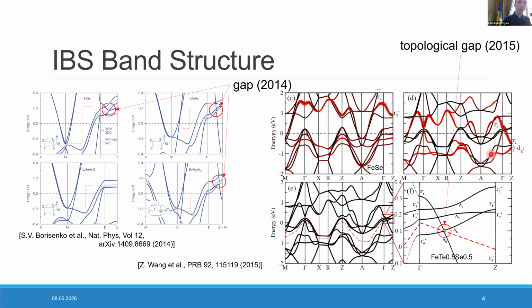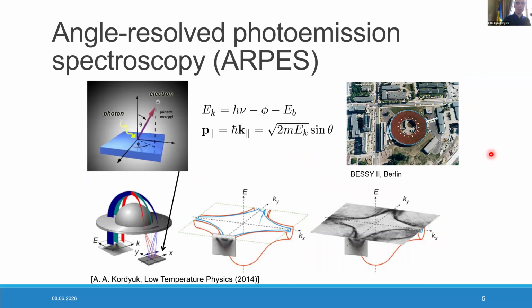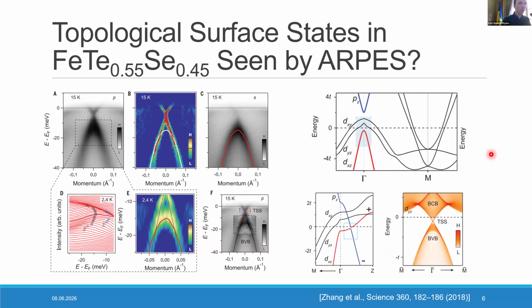And one of the ways to check that, and how people do that, is to do scanning tunneling microscopy to search for zero bias peaks, which are signatures of Majorana zero modes, but they can be strongly intertwined with other peaks coming from CDGM, and it's tricky. So the better way to do it, or rather to complement that, is of course ARPES. I won't stop too much on that. Sergey Sharapov earlier today gave a great talk and covered the technique in great detail. So I'll just move to one of the materials on which there were a lot of inconsistencies and controversies: iron, tellurium, selenium with 55% of tellurium and 45% of selenium.